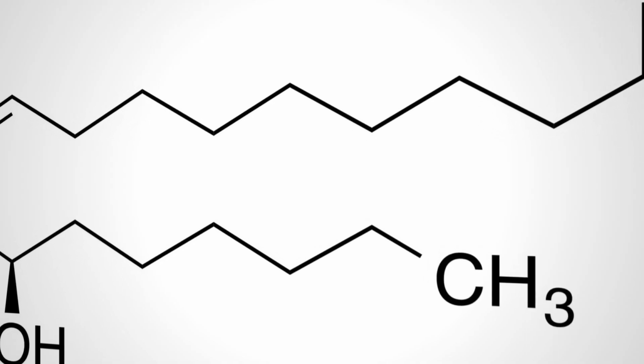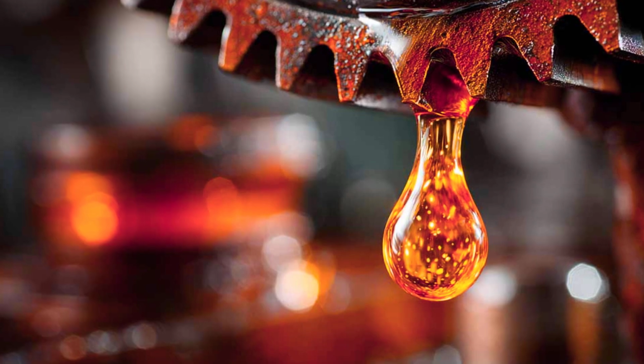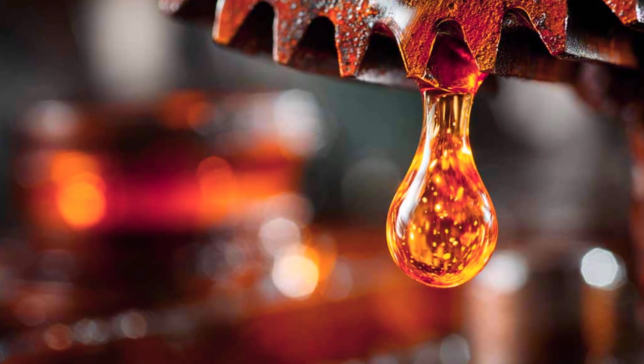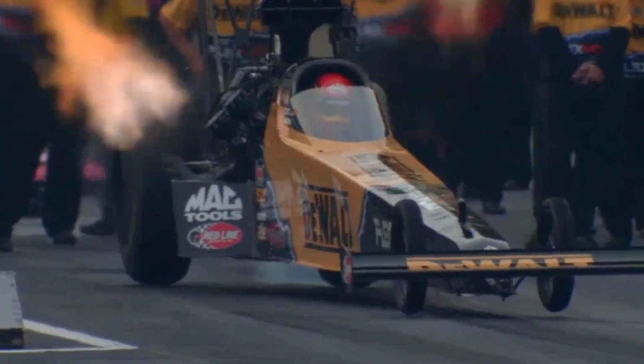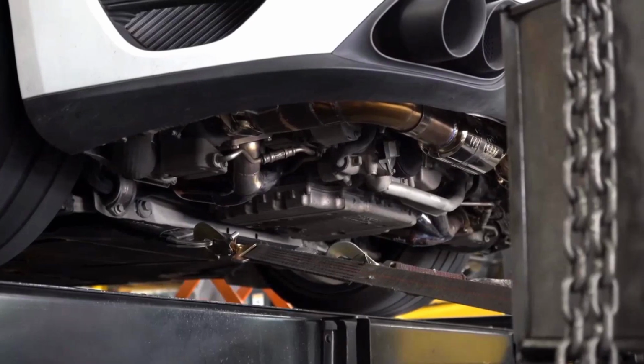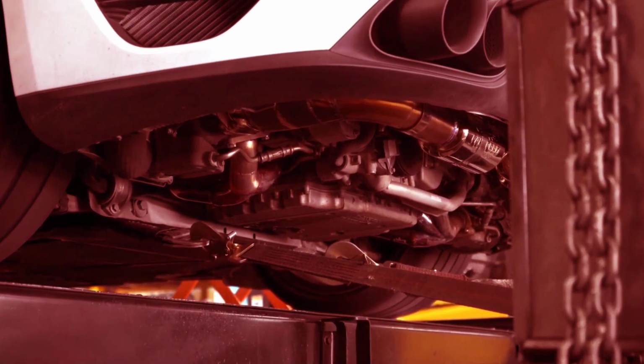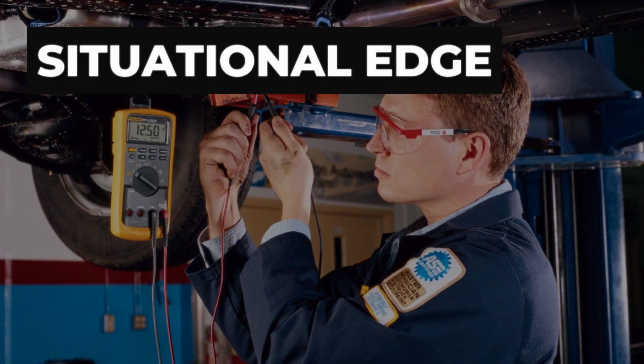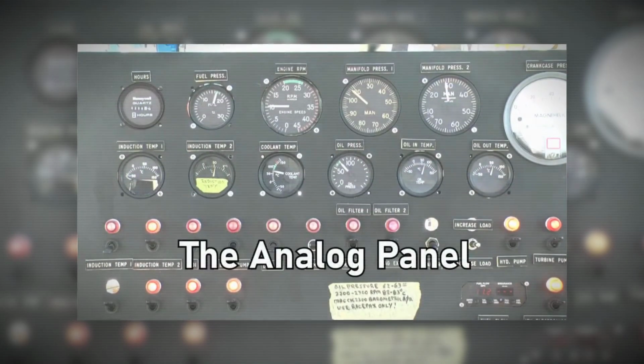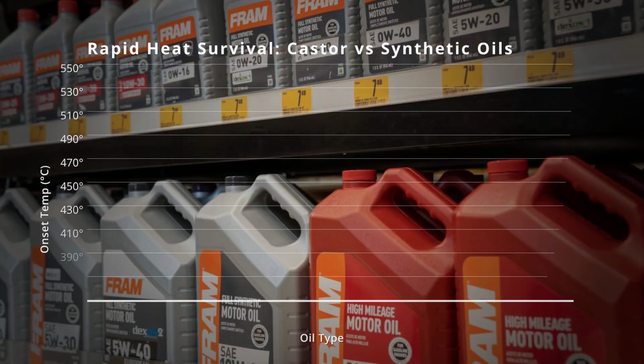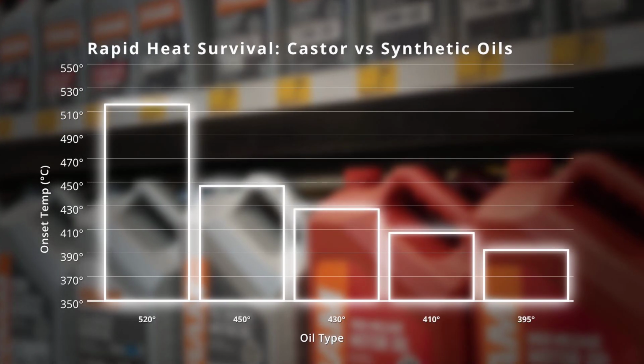Ricinoleic acid molecules link together under stress, building a glassy, protective layer right where the metal needs it most. This is not the slow, steady protection of long-drain synthetics. It is a last-stand defense, perfect for short, brutal sprints where catastrophic heat would strip away lesser films. But the edge is situational. When the test shifts to long, low load cycles, synthetics regain their advantage, outlasting castor oil by orders of magnitude.